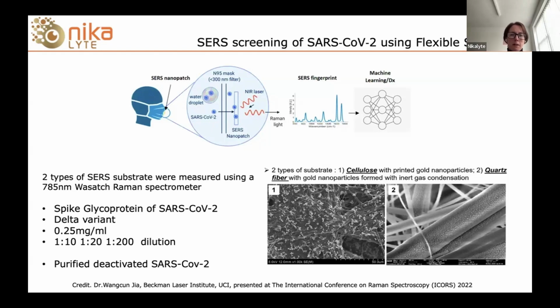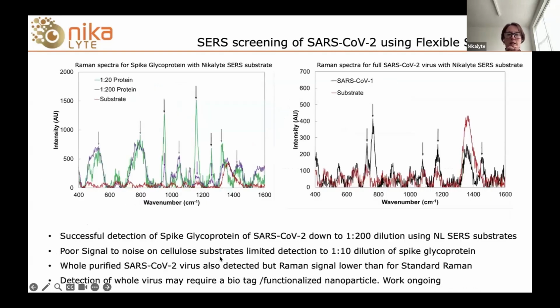So for the particular experiments that Dr. Gia did, he looked actually at two types of substrate. He looked at the Nikalyte substrate, which was number 2, but he also compared some cellulose substrates, which were also printed with colloidal gold nanoparticles, just to have two different references for the experiment. And in that experiment, the analyte that he was looking at was a spike glycoprotein of SARS-CoV. This was a Delta variant, and he looked at 0.25 milligrams per milliliter in 3 different dilutions. He also did some measurements on a purified, deactivated full SARS-CoV virus. So let me move on to some data.